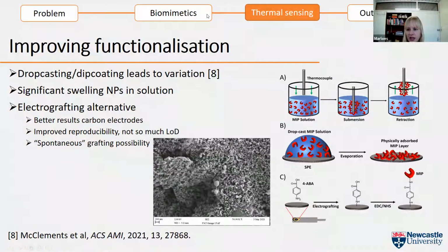So surface coverage is like 80–90%. And hopefully in the SEM, which is not the nicest because it's on a carbon electrode where you have lots of, it's not as nicely controlled as a gold surface. But hopefully you can see that the little dots are lots of nanoparticles that we have around. But the images we have on gold are a little bit better.